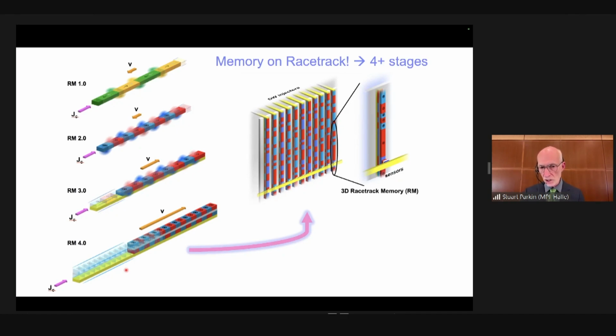Today, we have alternative methods of creating spin polarized current or pure spin currents by passing current through neighboring layers. In this cartoon, it's shown as this yellow layer. This is a heavy metal like platinum or tungsten, in which the electrical charge current is converted to a transverse spin current through a very different principle, the so-called spin Hall effect. And the spin currents diffuse into the synthetic anti-ferromagnetic racetrack, and they provide angular momentum and provide torques on the domain walls to cause them to move.